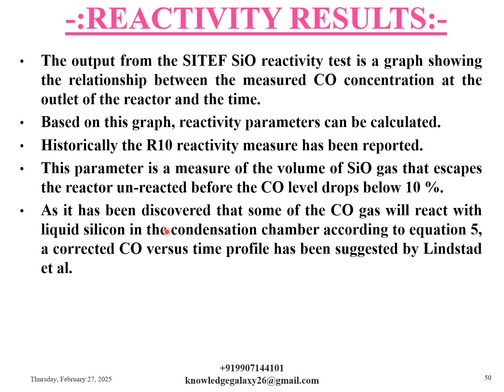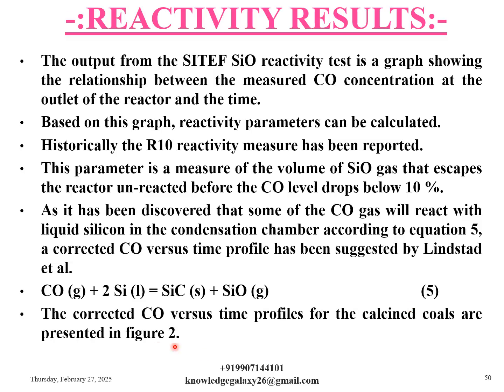As it has been discovered that some of the CO gas will react with liquid silicon in the condensation chamber, according to equation 5, a corrected CO versus time profile has been suggested by Lindstad et al. The equation is CO gas plus 2 silicon liquid gives SiC solid plus SiO gas. Equation number 5. The corrected CO versus time profile for the calcined coals is presented in figure 2.